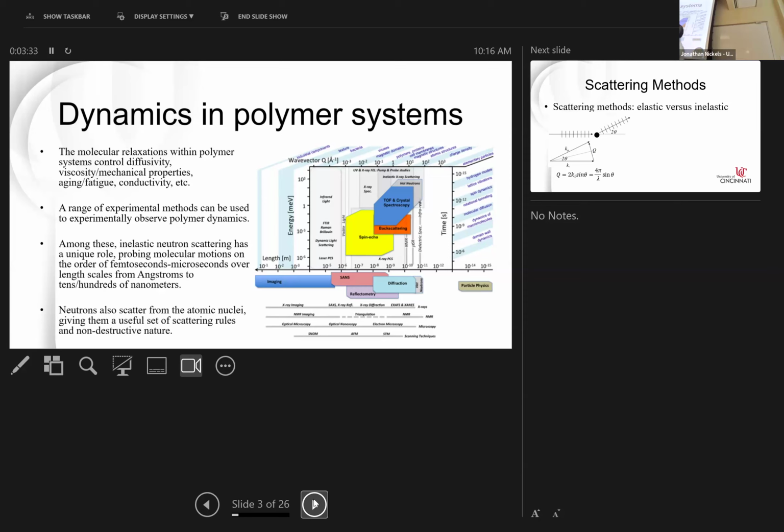Depending on what particular piece of that you're looking at, what type of property of the polymer you care about, what element of its structure, you're going to use different methodologies to study this. And so you can see some more benchtop or other types of techniques such as NMR or dielectric spectroscopy, infrared spectroscopy, light scattering of various flavors. They're missing some of these key windows where you care about the polymer dynamics. And that's why you end up needing to use neutron scattering techniques such as spin echo, backscattering, or time of flight spectroscopies. They sit right in the middle of this.